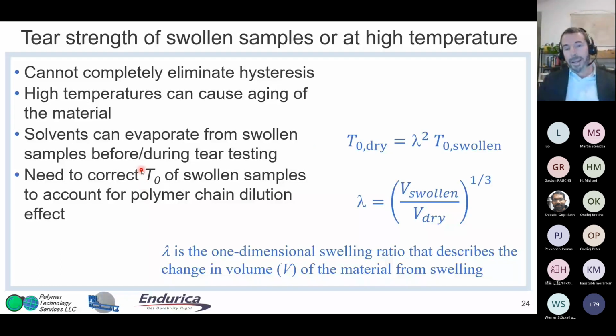Because remember, the crack has to break all the polymer chains. So if you put solvent in the system, you're basically diluting the polymer chain. So you have to account for that. So the swollen T0 ends up being a smaller value than the dry value. So you have to use the swelling ratio to relate between the two. And that just assumes that the only effect of solvent is just on pumping up the volume and diluting the system. Certainly it could have other effects on the tearing of those polymer chains that really is not accounted for in this kind of analysis.